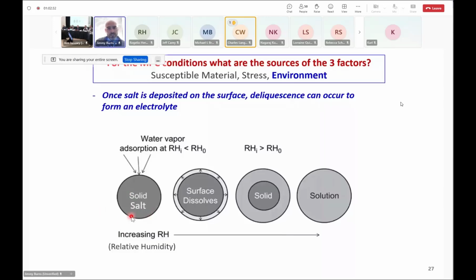And so deliquescence, what is that process? Well, you would have a solid salt. Let's just say, have an example here. You just have some solid aerosol salt that lands on the surface, dries out, and you just have a solid salt. At sufficient relative humidities and low enough temperatures, that salt can start absorbing water. And if you have a sufficient relative humidity, it can completely dissolve and create a solution.